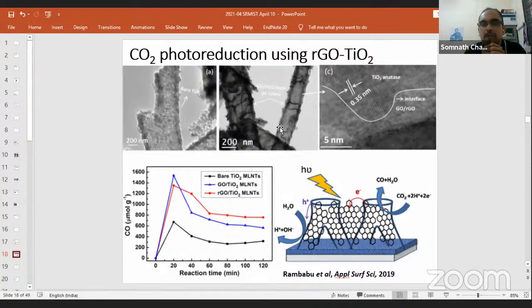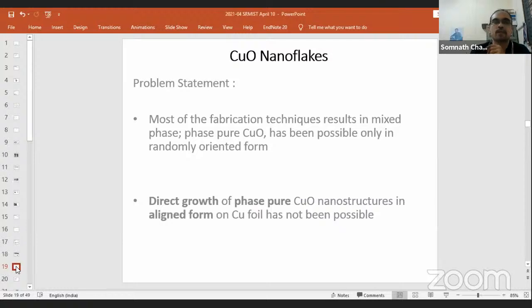One of the works we did around 2018-19, when we didn't have facilities, was done in collaboration with CSIR IIP Dehradun, Dr. Sumanlata Jain's group. We also tried to check photocatalytic CO2 reduction with the graphene oxide wrapped nanotube, and of course we found some initial increment, and we are still pursuing this work. Now we have facilities here in my lab at IIT Madras, where we are active. Now I will come to copper oxide.